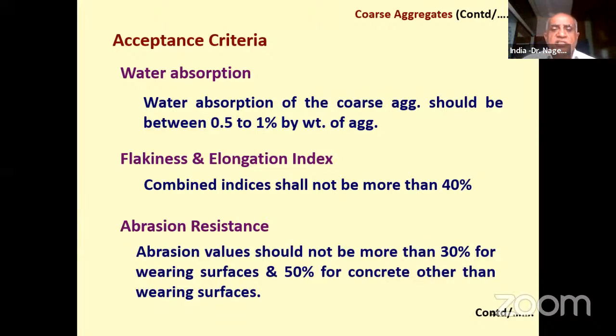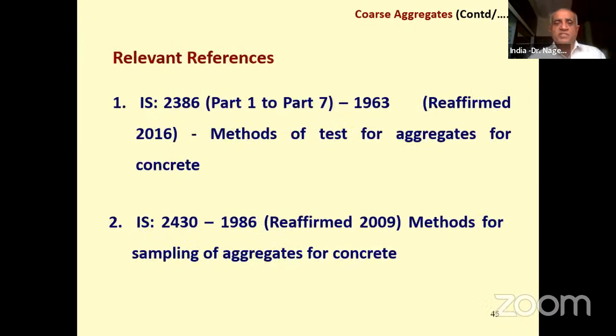Abrasion resistance is 30% for wearing surfaces, 50% for concrete and other non-wearing surfaces. You need not have very high quality, with less than 30%, for anything other than wearing surface construction. It can be slightly more. But in the case of wearing surfaces where there will be continuous movement of vehicles, the abrasion resistance is equally important. That's why it is restricted to 30%.